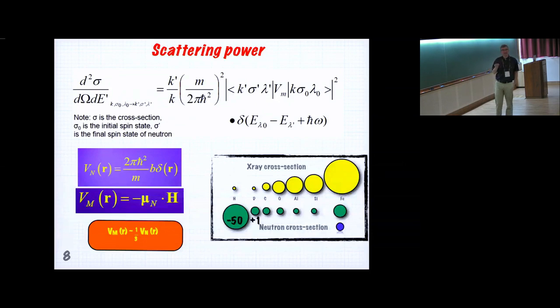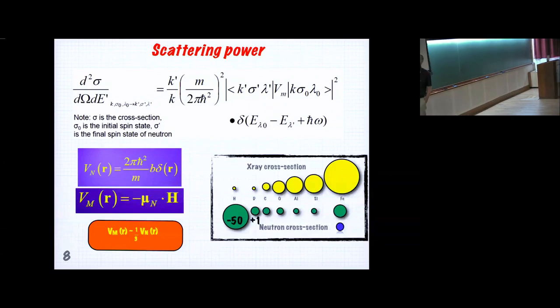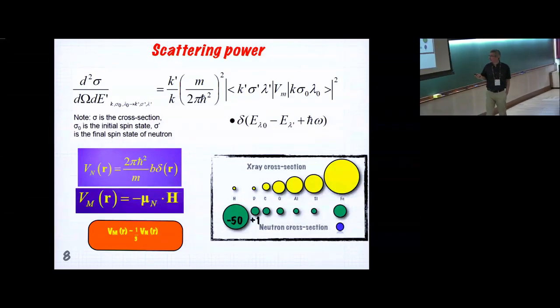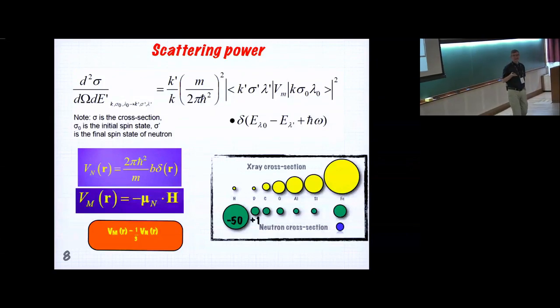With neutrons, that interaction strength here is isotope dependent. So for hydrogen and iron, actually hydrogen is much bigger. Hydrogen diffusion in metals was a huge topic many years ago, and it was mainly due to this. But it's also isotope dependent, and the classic that we show is hydrogen and deuterium, which are so different. So especially in soft condensed matter, they can deuterate a sample and put deuterium in certain places in a protein crystal structure or in polymers and probe a certain area of your sample.